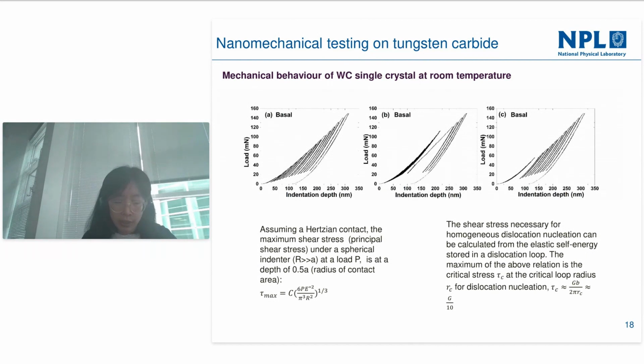We did a lot of analysis for single crystal tungsten carbide regarding the surface defects. As plastic deformation is believed to occur by the glide of pre-existing dislocations, whenever the stress field is large enough to trigger the dislocation motion, the pop-in could occur even during the unloading process. By reducing the indenter size, we were able to get a consistent load at which the pop-in occurs, which was further calculated to be quite close to the theoretical shear stress necessary for the homogeneous nucleation of the first dislocation loop, as shown in the following details.